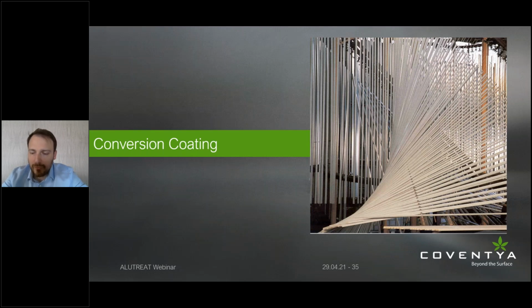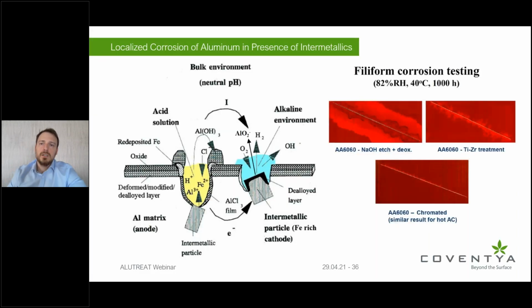So when we switch to conversion coating, obviously powder coating is very popular, especially in today's world, as an application for surface protection for aluminum. But the problem with powder coating is, because it's a foreign material applied on the surface of the aluminum, it is subject to filiform corrosion, where, as you can see here, due to the presence of intermetallics and aggressive ions, these filament-like corrosion products creep underneath the paint and give you a